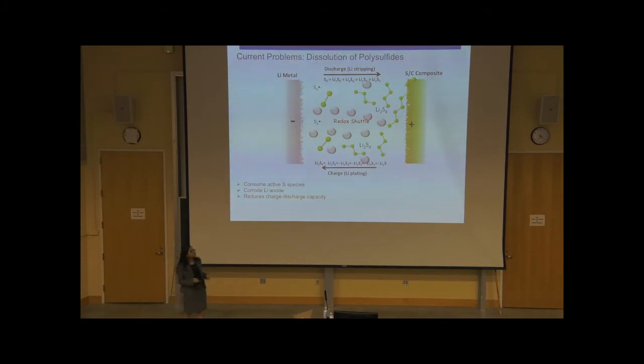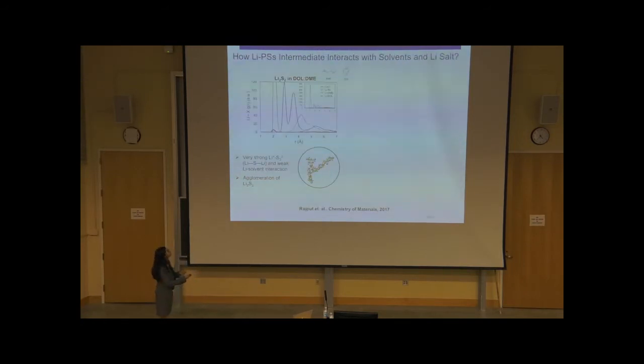So a lot of effort to overcome this shuttling phenomenon has been devoted to somehow suppressing these polysulfide species from moving toward the lithium, toward the sulfur side. So we want to suppress these sulfide species so they remain here by using some sort of membranes and porous material. Unfortunately, when we add any additional component into a lithium sulfur battery, it reduces the much needed capacity and energy density of these batteries. So our approach is to design optimal electrolytes by understanding their molecular structure so that we can resist the high dissolution of polysulfide species.